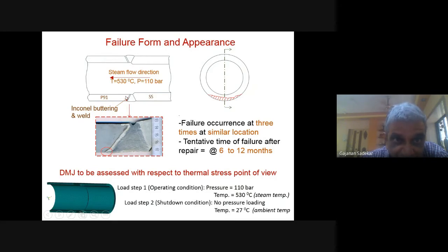Because you cannot weld the stainless steel directly with the alloy steel, they used to weld the stainless steel first, along with the stainless steel. Then they used to put the Inconel material on it. That's called Inconel buttering. And then Inconel to P91, that is the alloy steel, used to be welded. This is the configuration of the weld.